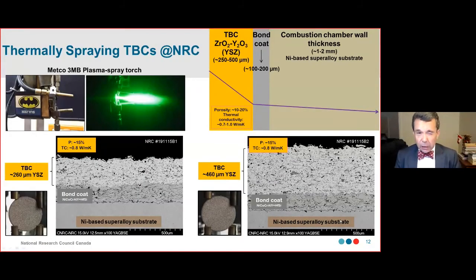So Amy has a question about the microstructure on slide 12. She wants to talk about the porosity levels of the bond coats. What are the acceptable porosity levels on bond coats? She's referring to slide 12. Okay, so basically, as a kind of thumb rule, people would prefer to have porosity of the bond coat less than 5%.